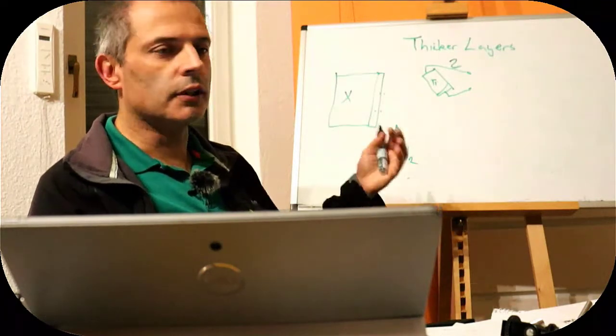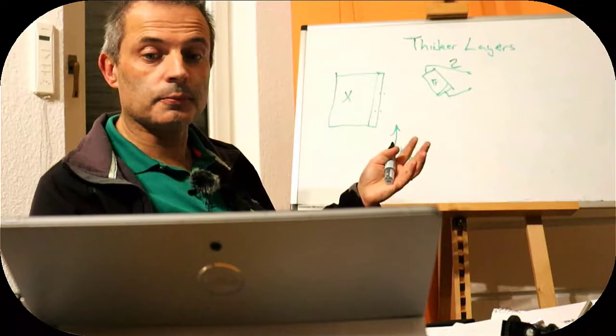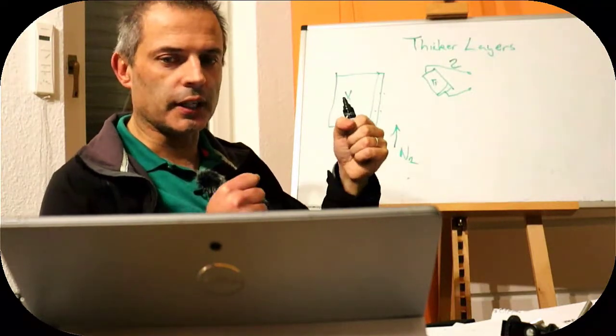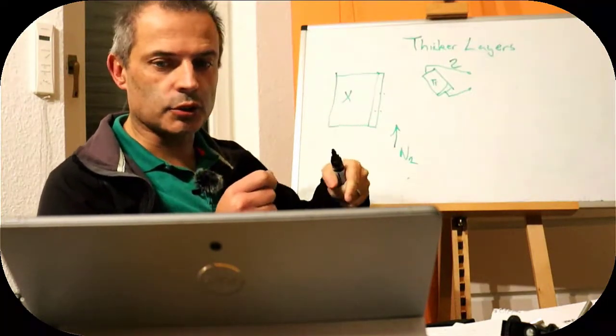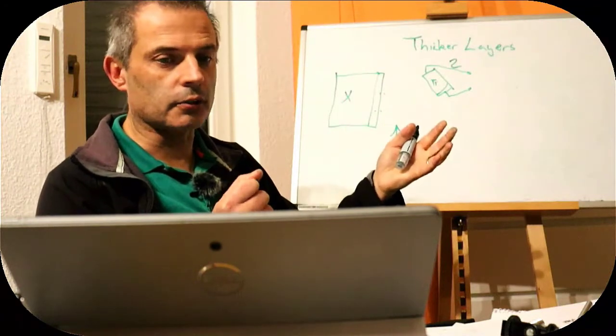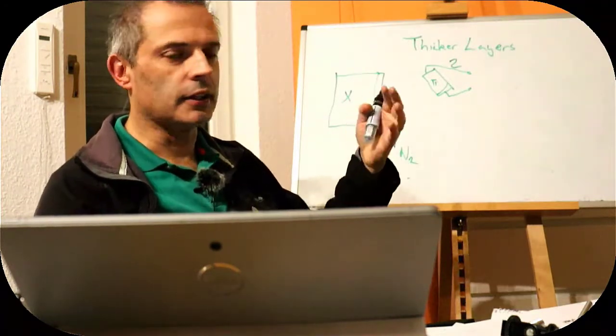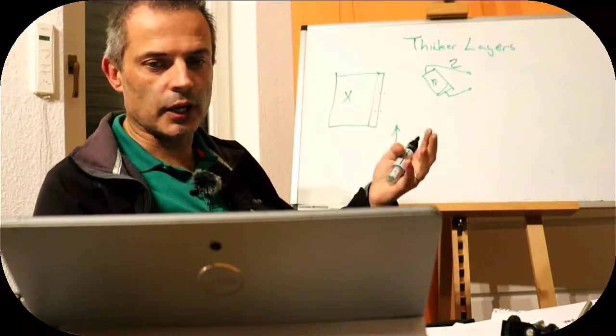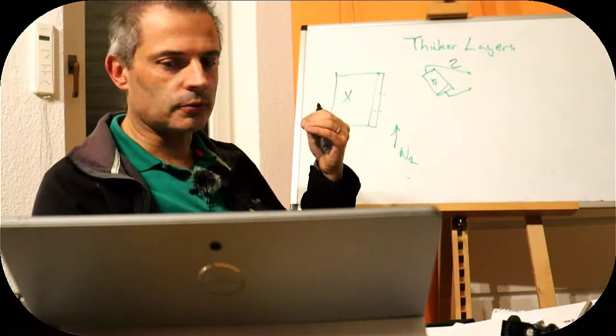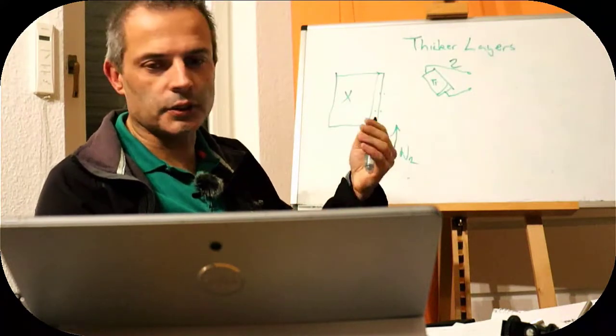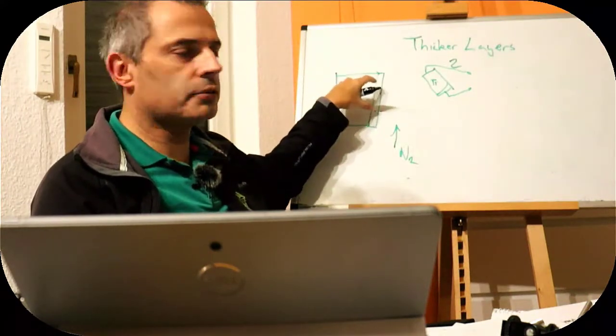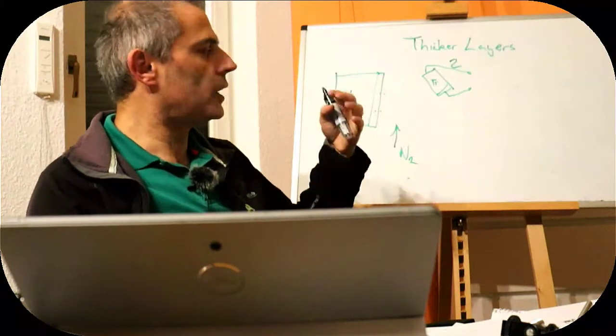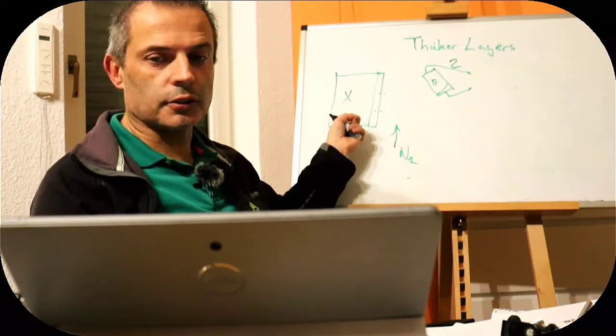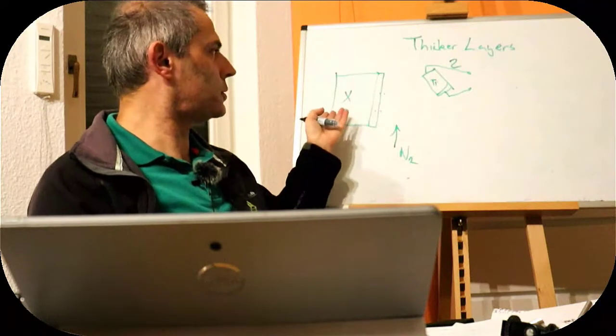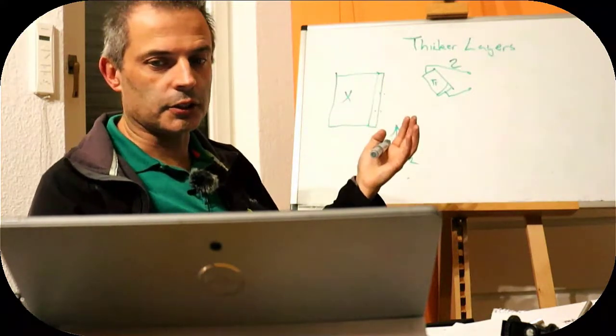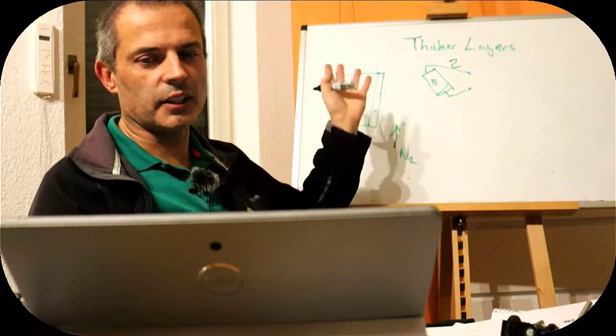If we're generating a material that is brittle, if it is compressed together, if we generate a crack in it, if we scratch the surface to start a crack, if it's compressed together, that's good because it will keep the crack shut. So from normal materials properties, ideally we would have compressive stress in our film, and a little bit of tensile stress in our substrate, but our substrate is very much thicker, so it's not going to damage it unless we only cut one side, and then it might bend slightly.